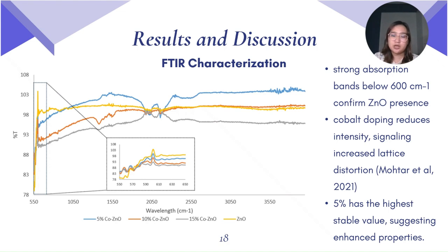Increasing cobalt concentrations to 10% and 15% result in further peak broadening and intensity reduction, signaling increased lattice distortion and defect formation. These changes imply that although moderate cobalt doping can enhance structural and electronic properties favorable for photocatalysis, excessive doping introduces disorder that may adversely affect material performance. In addition, the 5% Co-ZnO sample had the highest stable value compared to the other samples, suggesting enhanced properties or stronger response at low doping concentration.